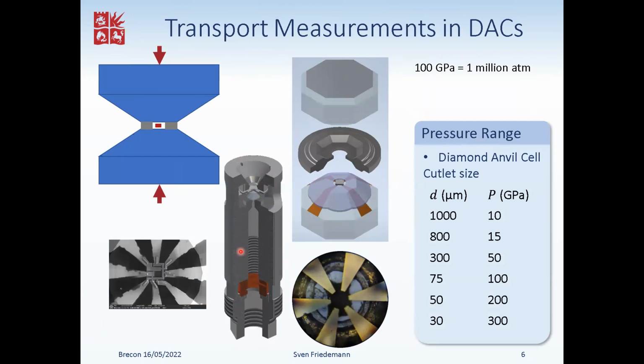Whilst the sample is certainly not a sphere, it's about 50, the H3S phase is about 15 micrometer laterally and about 2 micrometers thick. But this is not an enormous anisotropy, and it's not an enormous demagnetization factor. So I don't expect much dependence on the orientation of the field here.